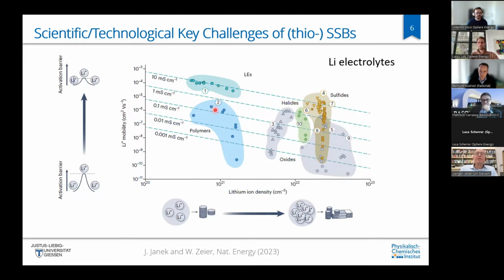And this is the reason, of course, why at the same charge carrier concentration, polymers are attractive. However, true solid polymer electrolytes have too low a conductivity. That's why you gellify them, or you bring in solvent to make gel polymers, which have this higher conductivity and then allow the construction of batteries.